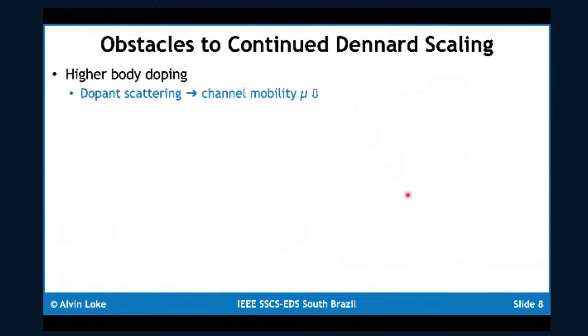There's been several obstacles to continue Dennard scaling, and as we mentioned, the way to deal with having thinner and thinner depletion regions is to have higher body doping. One of the consequences of having higher body doping is more ionized impurity scattering, which causes your channel mobility to degrade and therefore your current to degrade.